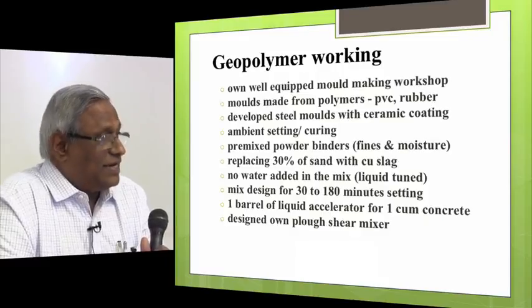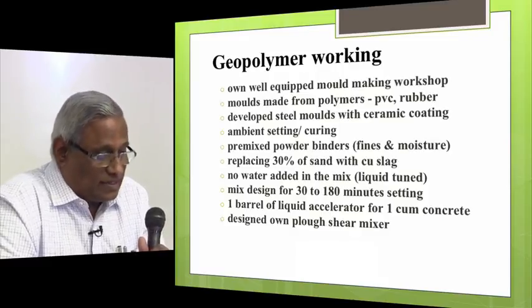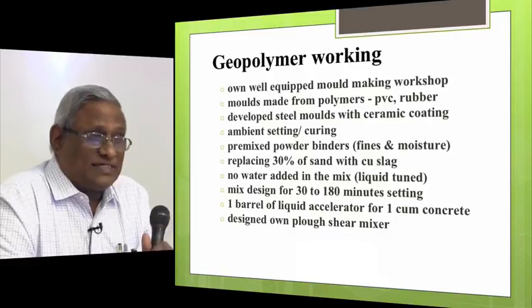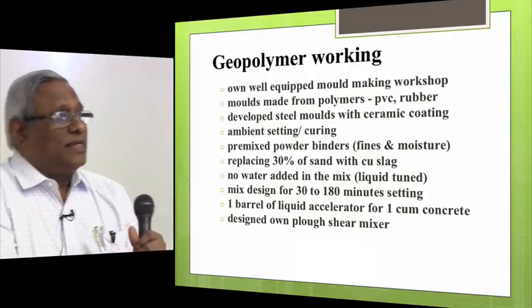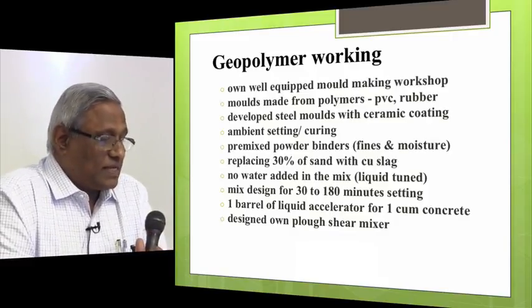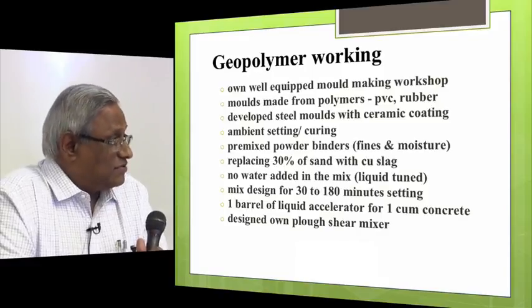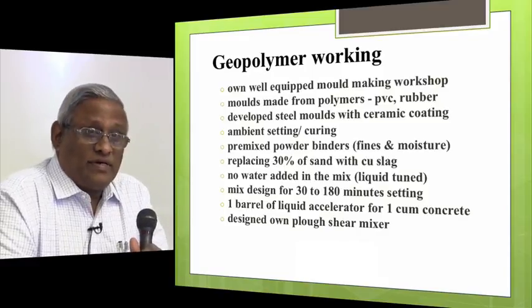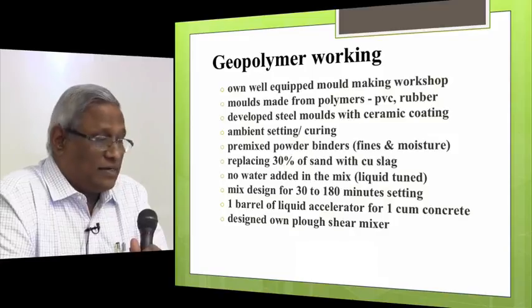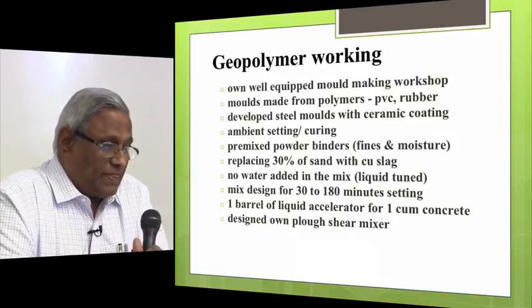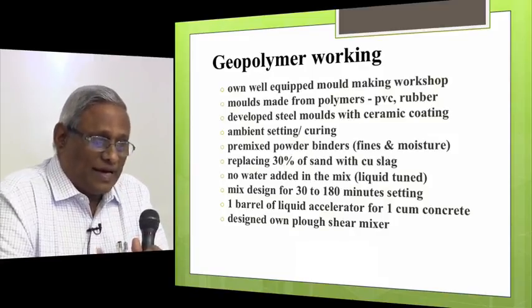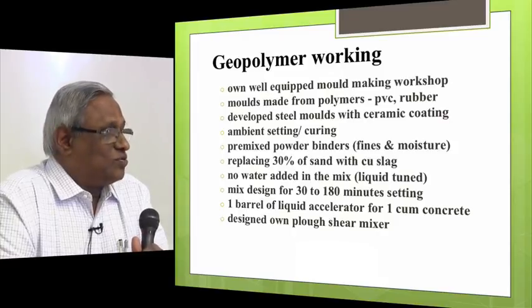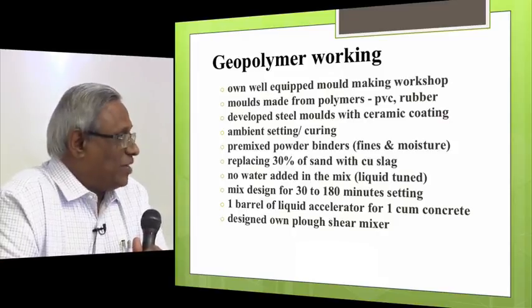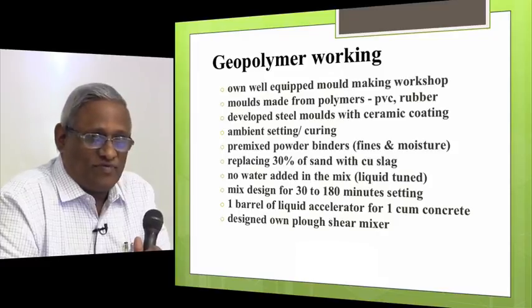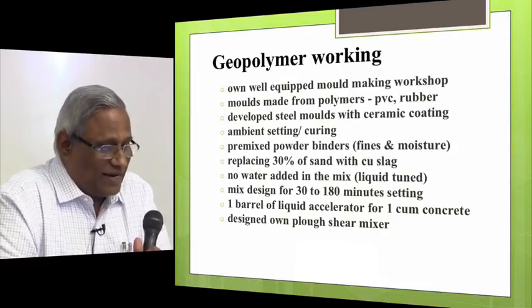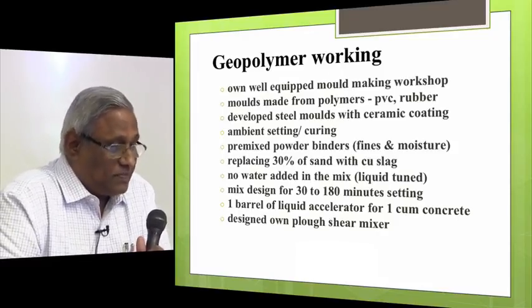We can give you a mixed design of different types of accelerator and the combination of powder binders, which can set between 30 and 180 minutes. It's required in some cases. You need a faster setting, and when you want to have a ready mix concrete, you need a longer setting. And just a thumb rule, a barrel of accelerator, about 250 kilos, you can make 1 cubic meter of concrete. It's just a thumb rule for you. It may vary a little here and there.